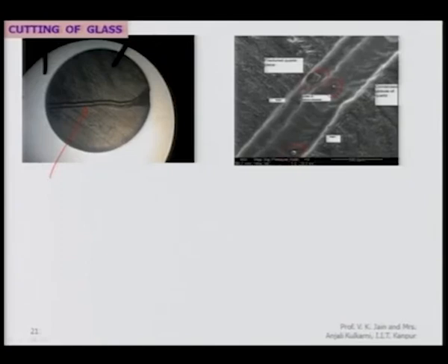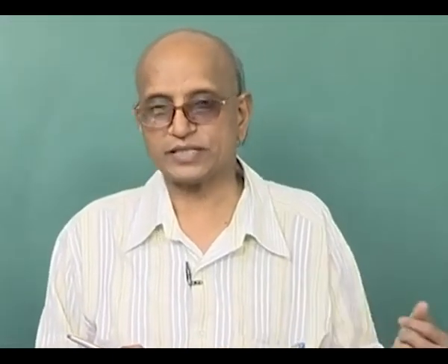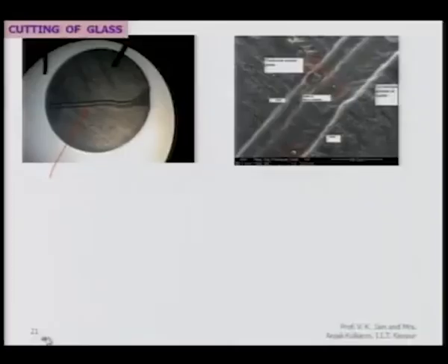That means, due to the micro crack, some material got removed from the parent material, and that is what is shown over there. But at most of the places you will find globular form of the material, because whatever is the molten or softened material gets solidified, and naturally it is going to be in the form of a sphere.